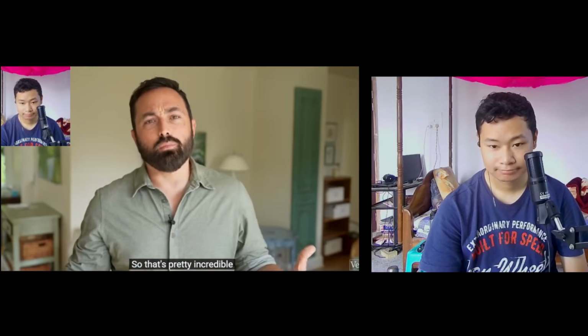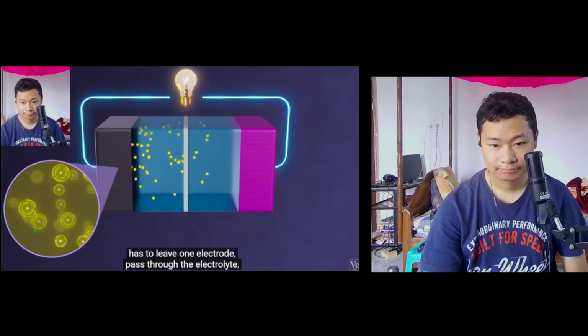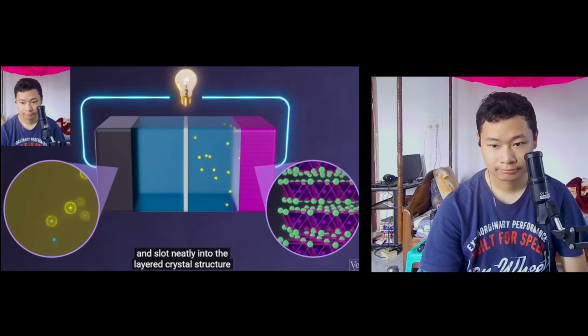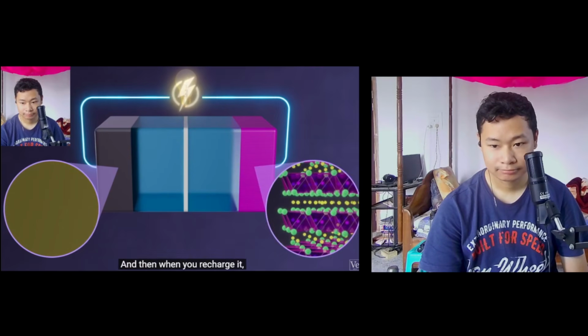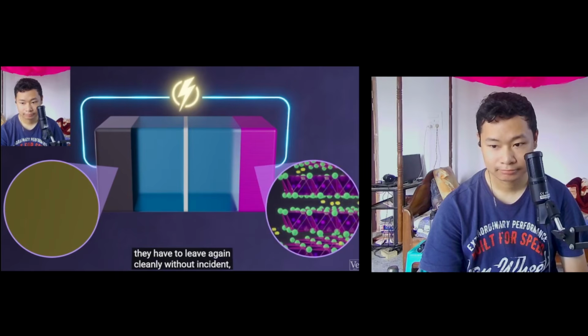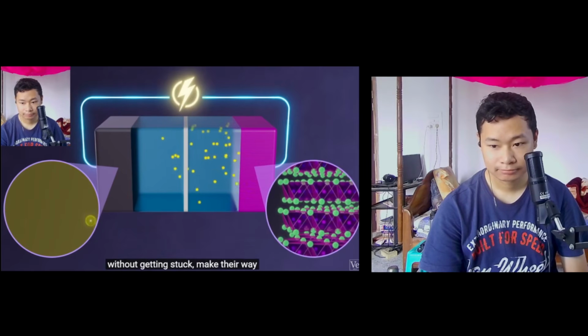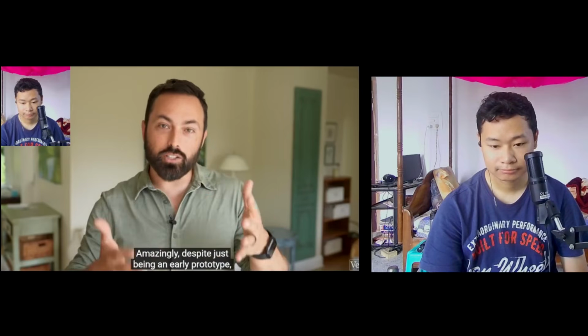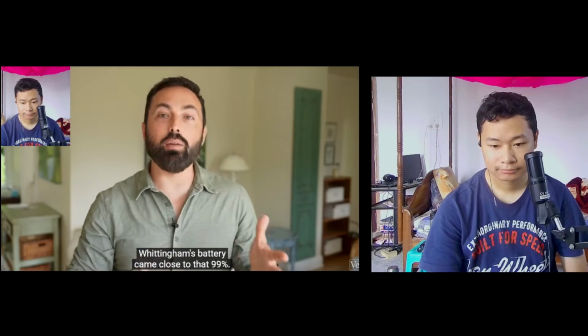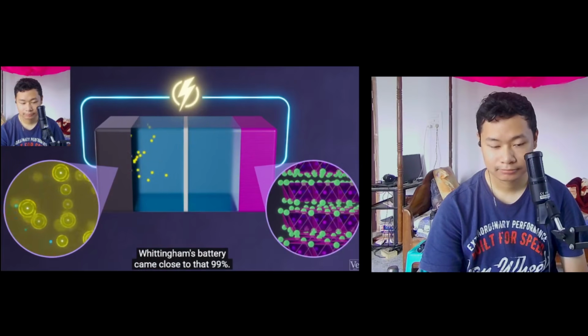If you have, say, a 95% yield, then you'd lose a significant fraction of lithium ions every cycle. After just 50 cycles, you'd only have 8% of your original capacity left. So that's pretty incredible that every single lithium ion has to leave one electrode, pass through the electrolyte, and slot neatly into the layered crystal structure of titanium disulfide, and then when you recharge it, they have to leave again cleanly without incident, without getting stuck, make their way all the way back to the anode. Amazingly, despite just being an early prototype, Whittingham's battery came close to that 99%.